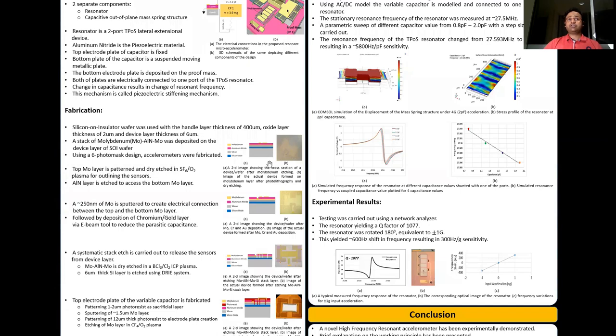This design was fabricated on a silicon-on-insulator wafer that had a stack of molybdenum, aluminum nitride, and molybdenum, and the whole fabrication was completed using a six-photo mask design.